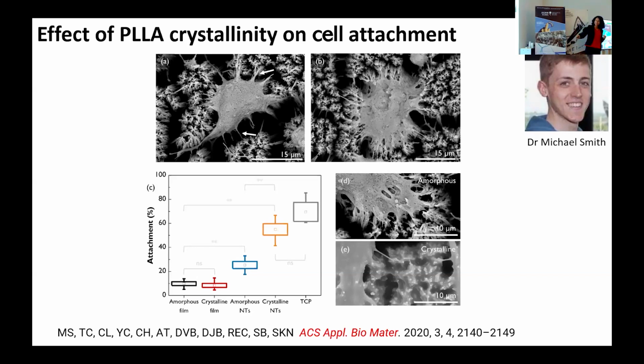So here we look at cell attachment for films of the material. They don't like the films at all, so almost 0% attachment. And here are the nanowires. You can see they attach more strongly to the crystalline ones than to the amorphous ones. And TCP is just tissue culture plastics. This is what people normally use. So this is as a control experiment. So we're like, right, the cells didn't do any X-ray diffraction, but somehow they worked out which was crystalline and which was amorphous.